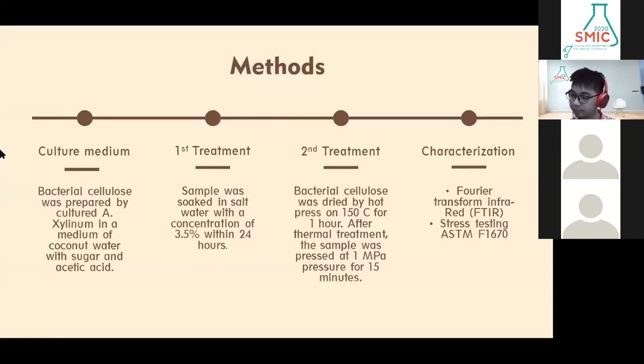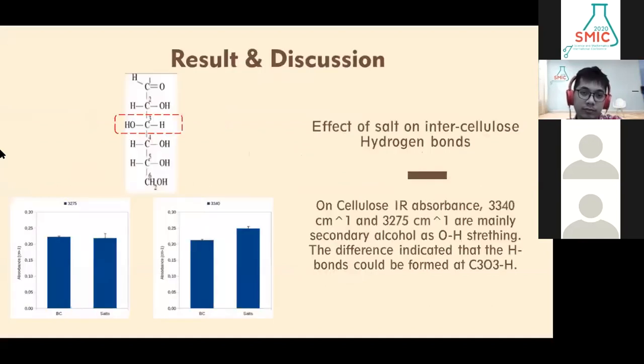After that, we dried the bacterial cellulose using a hot press at 150 degrees Celsius for 1 hour. After that thermal treatment, the bacterial cellulose was pressed at 1 megapascal pressure for 15 minutes. We use Fourier transform infrared spectroscopy and stress testing ASTM F1670 to characterize our bacterial cellulose. In the results, we look at the effect of salt on the intercellulose hydrogen bond. We choose 2 points of interest from the IR absorbance at wave numbers 3340 and 3275.